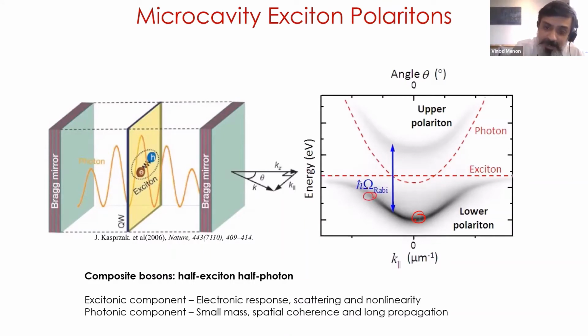If I go to larger values of k, where it becomes more exciton-like, the interactions are going to be much larger. So I can tune my interaction strengths, I can tune how far it propagates, all of this by manipulating the in-plane momentum of the polariton states that I want to look at. The other interesting property of this system is that the in-plane momentum inside the cavity is directly related to the angle at which the light is coming out. So you can use photons that come out as a signature or something that quantifies what is happening inside the cavity.